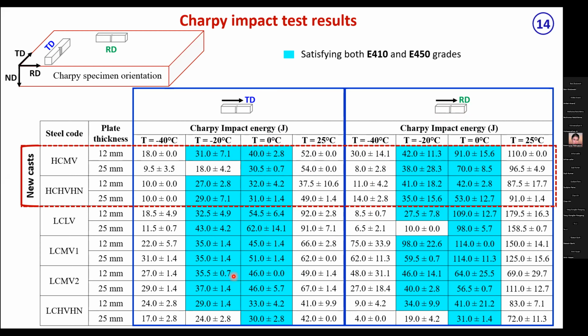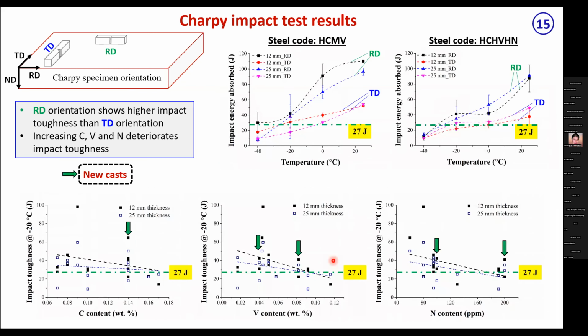In all the blue cases, we are exceeding toughness of 27 joule, which is the minimum required for structural purposes. So overall, we are meeting our properties, and we have found a good range of properties for all our compositions and products, even for the thicker 25 mm plate. Of course, there are a few exceptions where we got slightly lower properties in the longitudinal direction, which we have to investigate. But otherwise, it's quite a decent result.